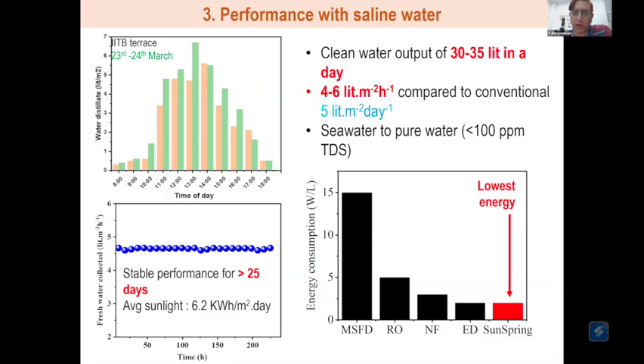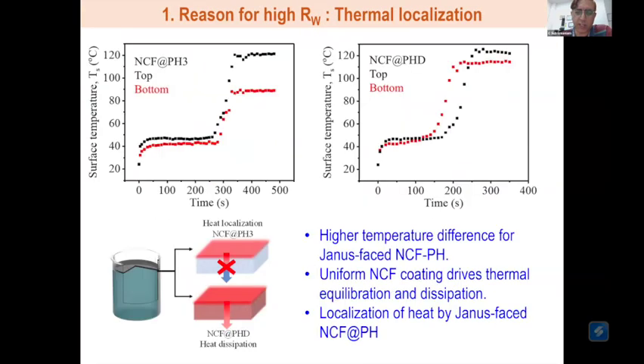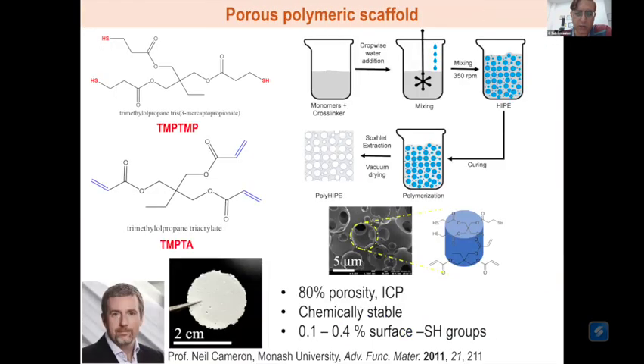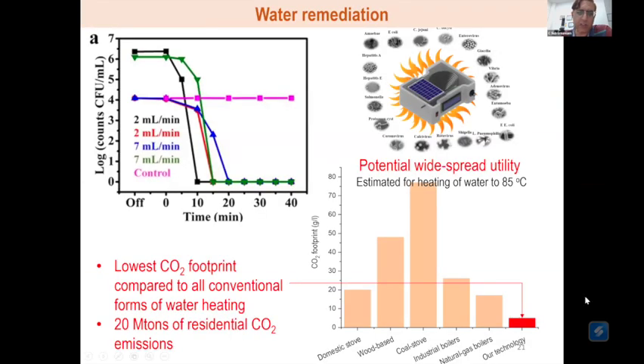The other thing that I want to point out in this energy consumption is that all these techniques, the ones given in black, constantly require electrical energy to be fed into them for the process of water purification. Here, it's all dependent on solar, and that is why we have one of the lowest carbon and energy footprints. If you look at another statistic, which is for just heating water, I can show you this slide, which is the CO2 footprint in gram per liter. If you want to take 1 liter of water to 85 degrees, what's the CO2 footprint? This is going to be extremely low. This footprint, which is roughly about 5 grams per liter, compared to something like a coal stove or even an industrial boiler, is 1 order of magnitude lower.